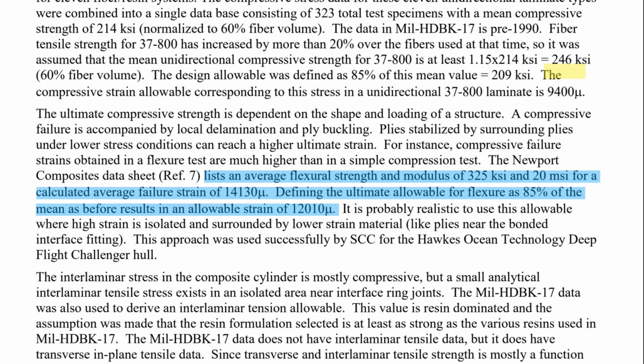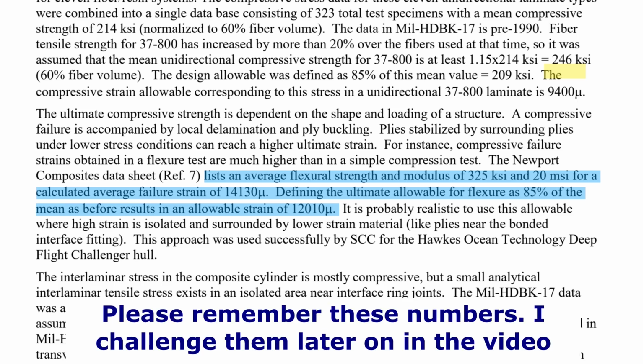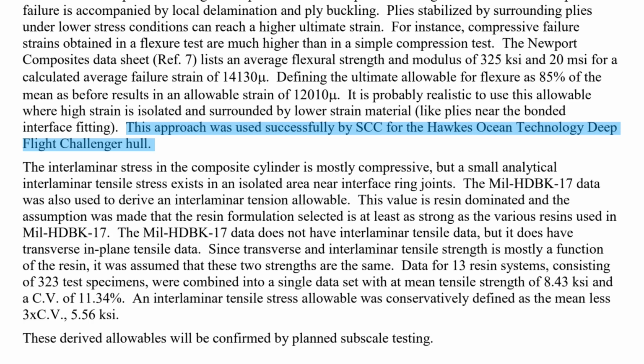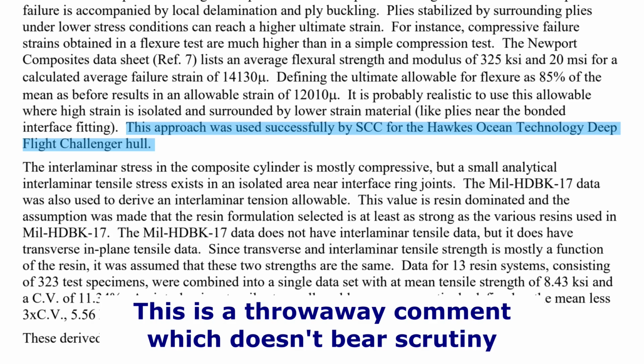And they quote a failure stress of 325 KSI and failure strain of 14,000 microstrains. And they argue that this value should be used at the interface between the carbon fibre and the titanium ring. They furthermore say that this was used successfully by Spencer Composites for Steve Fossett's Hawkes Ocean Technology Deep Flight Challenger hull. Well, that sounds very impressive, but to the best of my knowledge, this hull has never been used and has never been pressure tested, so I'm not sure how you can claim that it was used successfully.